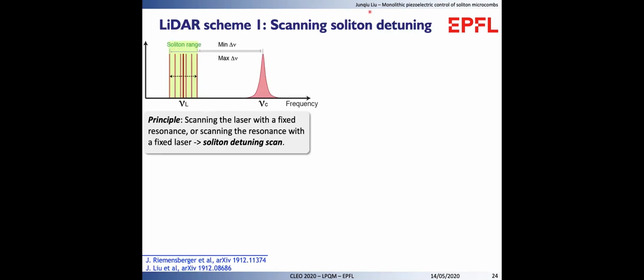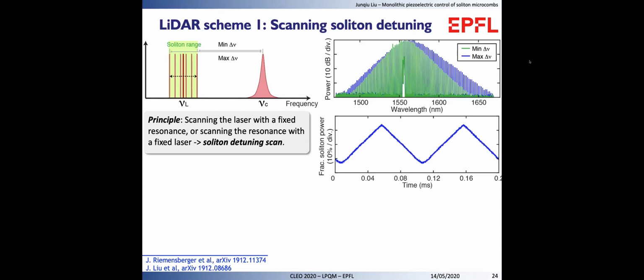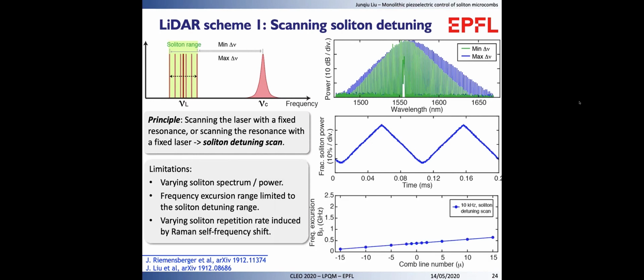There are two schemes to implement soliton-based FMCW LIDAR. The first scheme uses a fixed microresonator resonance and a modulating CW pump within the soliton existing range. This method manifests as a soliton detuning scheme. As a result of the varying soliton detuning, the soliton spectrum changes correspondingly, as well as the soliton pulse power. In addition, the frequency excursion cannot exceed the soliton existing range. Furthermore, when changing the soliton detuning value, the soliton-induced Raman self-frequency shift also changes the soliton repetition rate. In the end, the frequency excursion of each comb line is not equal, as shown here, which results from the change in the soliton repetition rate.